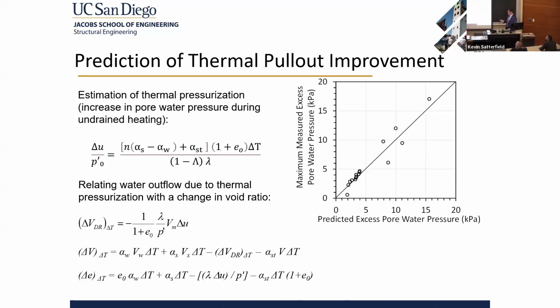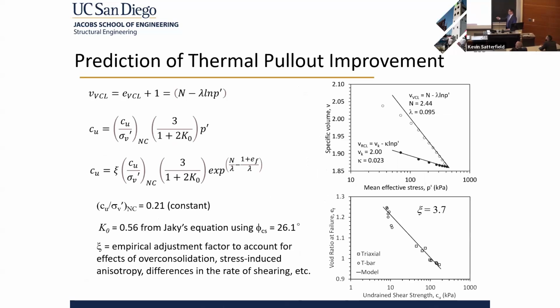So this is our pore pressure equation, measured versus predicted. We got a pretty good prediction there. And then we know that if we have a change in void ratio, we should also have a change in undrained shear strength. So we used the Cam Clay model, as we have a normally consolidated soil in this case, to obtain the undrained shear strength as a function of void ratio at failure. And you can see that our measurements from our T-bar tests match up well with that model, with a correction factor to account for overconsolidation ratio and stress-induced anisotropy differences.